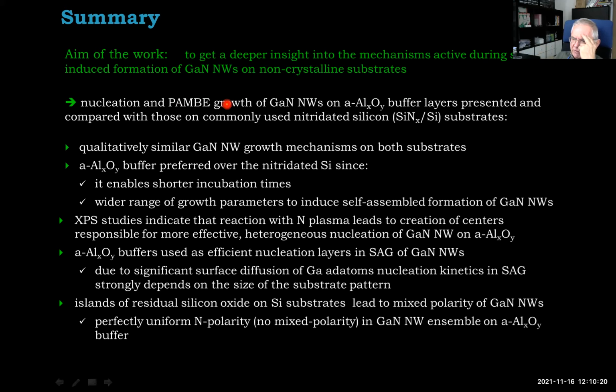We have compared nucleation and growth mechanisms on two types of substrates, and the conclusion is that the mechanisms are pretty much the same. Qualitatively, we have exactly the same growth mechanism on both substrates, meaning that probably we can expect that other substrates will show similar behavior, and that this mechanism is actually typical of the MBE growth method, plasma-assisted MBE itself. However, quantitatively there are differences. Short incubation time on aluminum oxide and a wider range of growth parameters to induce formation of nanowires.